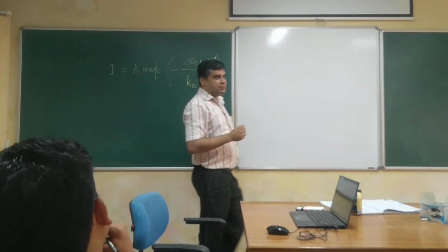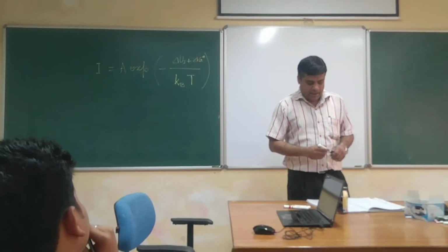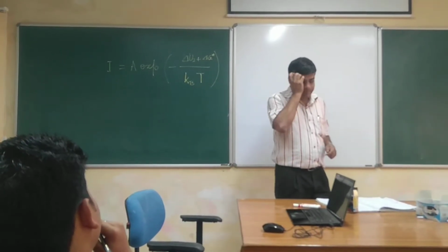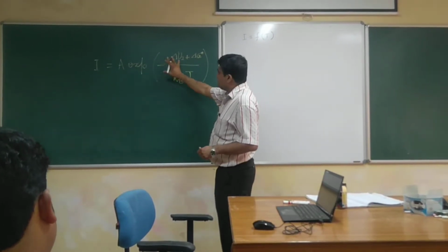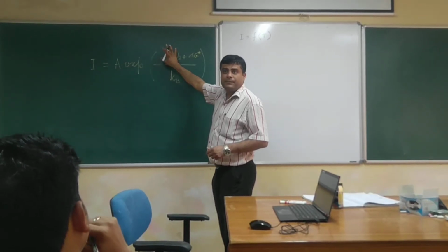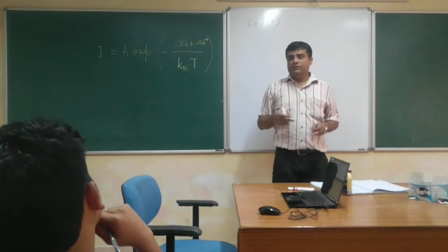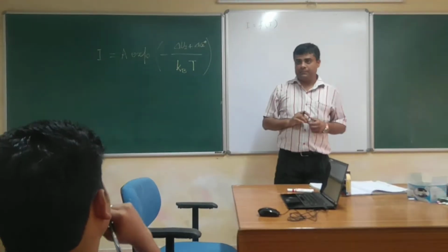Now, how is nucleation rate temperature dependent? As for the temperature dependence of nucleation rate, we have two terms. One is this one, and we said that delta UI, this activation barrier, is not very much a function of temperature. We can assume it's not a function of temperature.